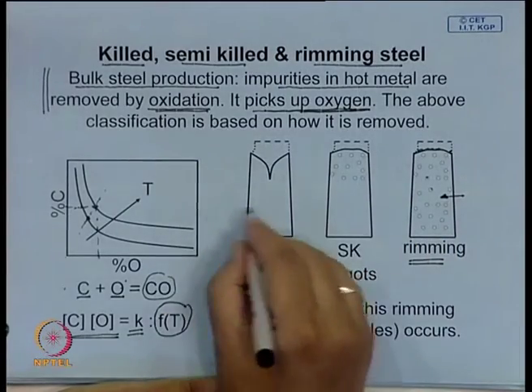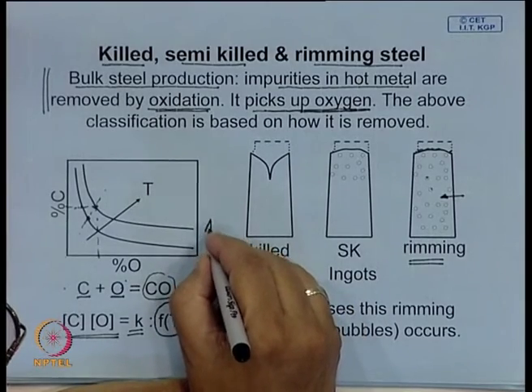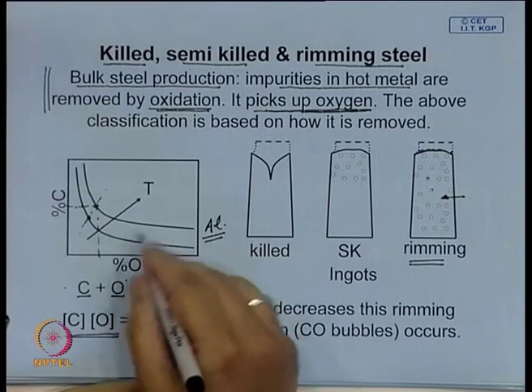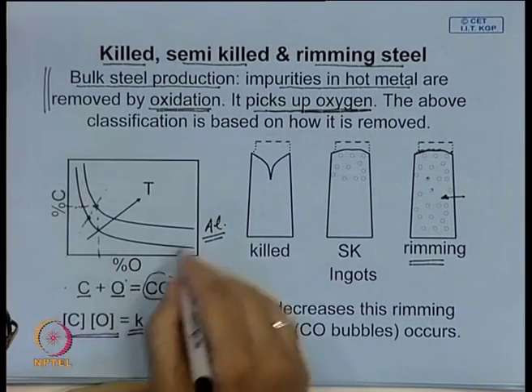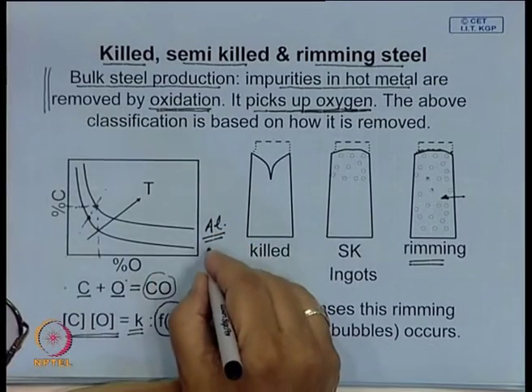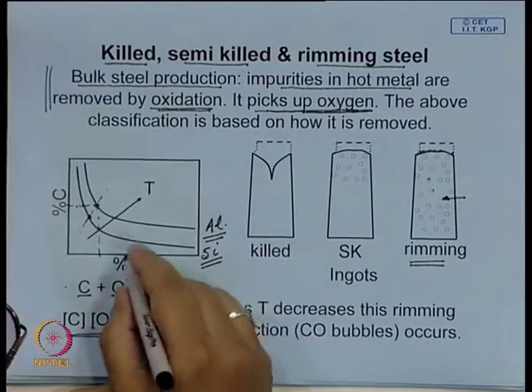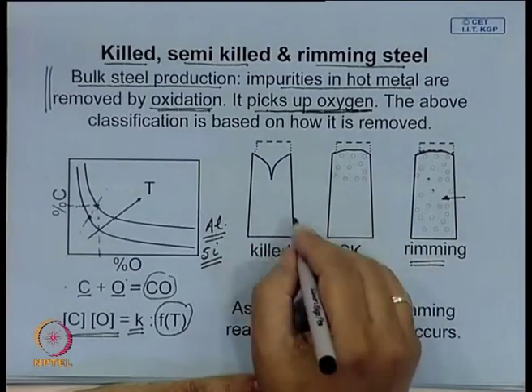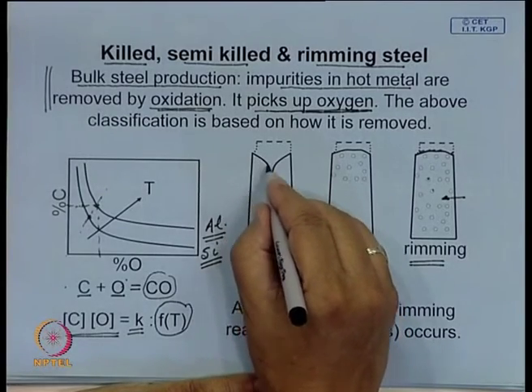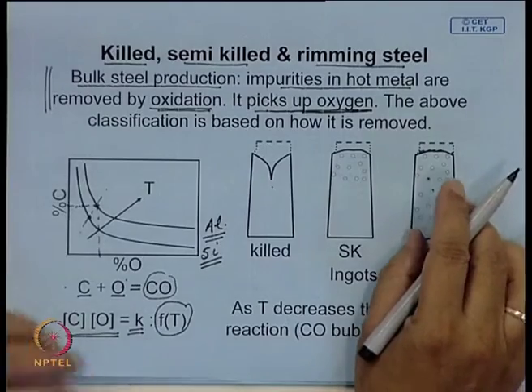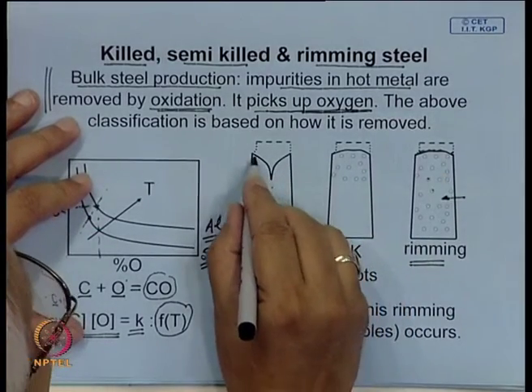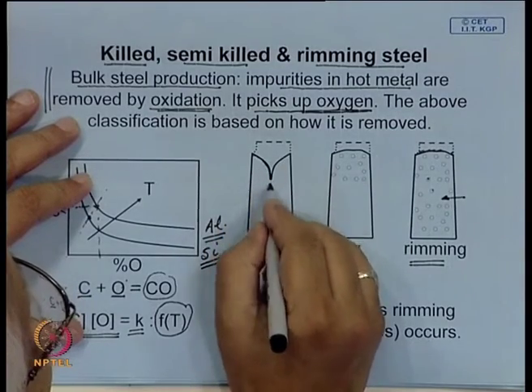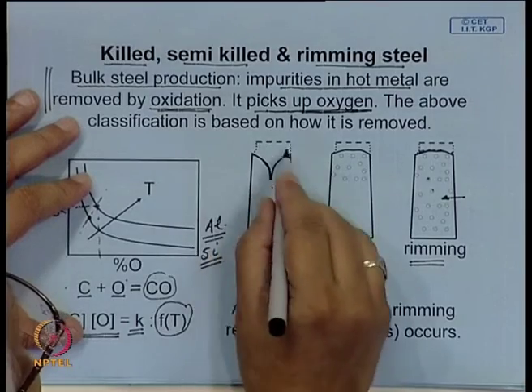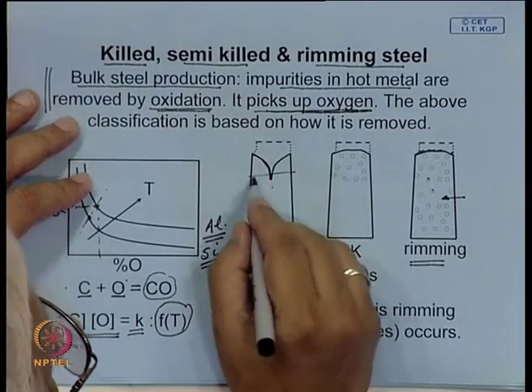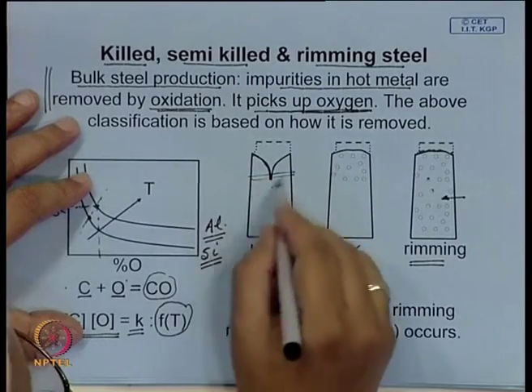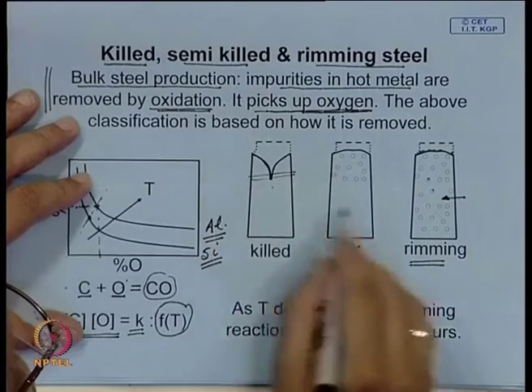At the other extreme, if you add a deoxidizer, and one of the preferred deoxidizers is aluminum, which has a very strong affinity for oxygen, then this oxygen will be used up by aluminum or silicon, depending on what you are adding. You can stop this rimming reaction completely, and in that case you kill this particular reaction. That means you kill the steel, which is very reactive, and therefore you get a large shrinkage cavity. When you roll, of course, the yield is low, because later on you have to crop a certain part of it which cannot be shaped into flat products or sections.